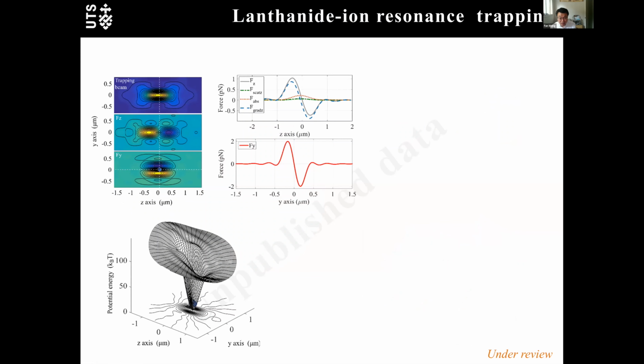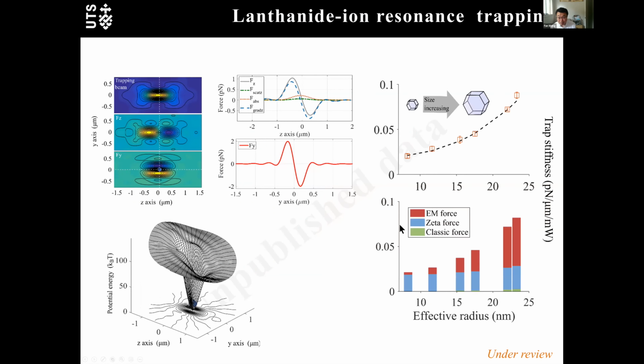Using this, we did some simulations, and we can see that as the size increases, the force keeps increasing, because we increase the polarizability. You will also see that when the particle is smaller than 10 nanometers, the zeta force, or the surface charge, takes charge. But if it's larger than this, your ion resonance force directly goes to really, really high.